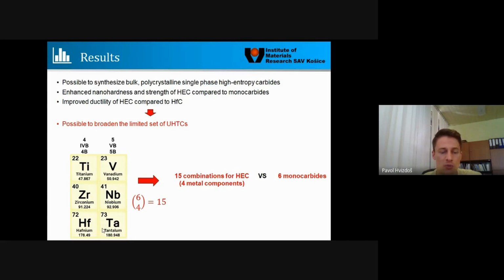So we have 6 options to form ultra-high temperature carbides. But if we select 4-element carbides, for example, the material that we just showed before, we have 15 options for how to select the 4. So instead of 6 monocarbides, we now have 15 4-metal element high entropy carbides which can be synthesized. So it gives a vast new compositional space for synthesizing new ultra-high temperature ceramic materials.